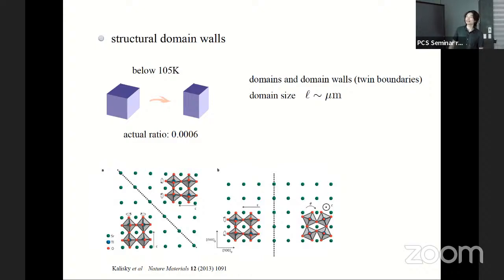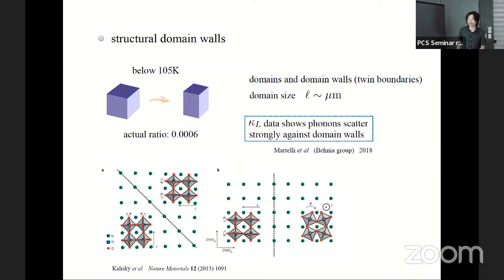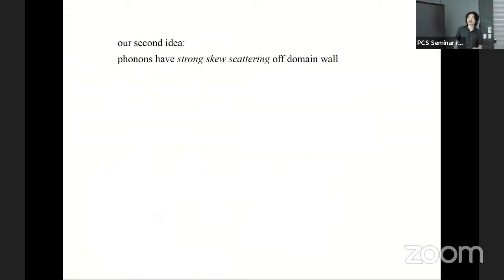Okay, so at low temperatures, there are indeed these domains and domain walls, and the domain size is of the micron scale. And you might recall that I mentioned something else is also the micron scale: the mean free path in this material is micron scale. So the Behnia group measured the longitudinal thermal conductivity. The longitudinal data shows that phonons indeed scatter strongly against the domain walls, so that when the domain wall separation is micron, the mean free path is also micron, which means the scattering probability of the phonons against the domain wall is of order 1, or the typical scattering angle is order 1. Okay? So indeed, there is a strong scattering.